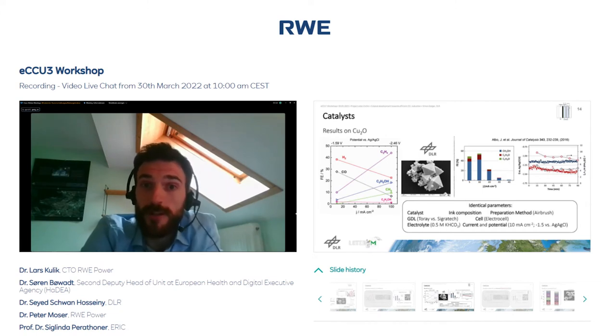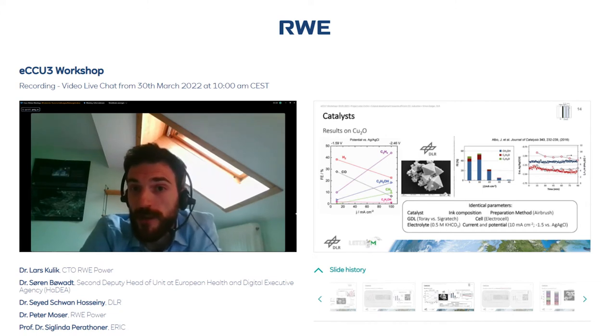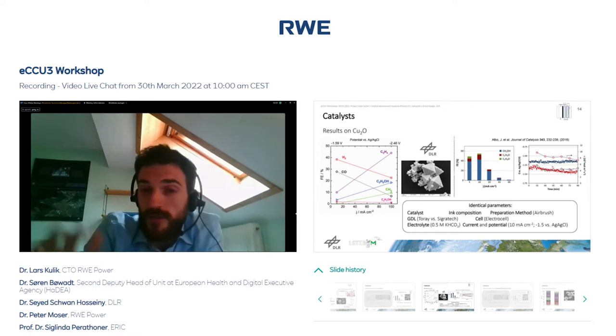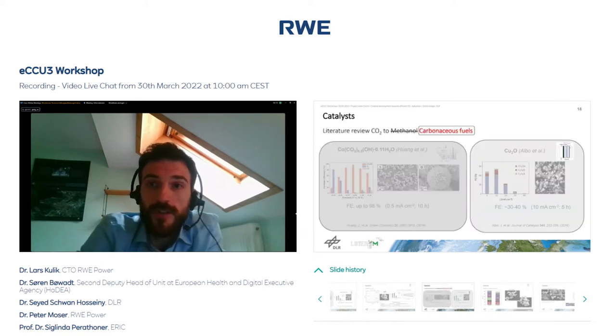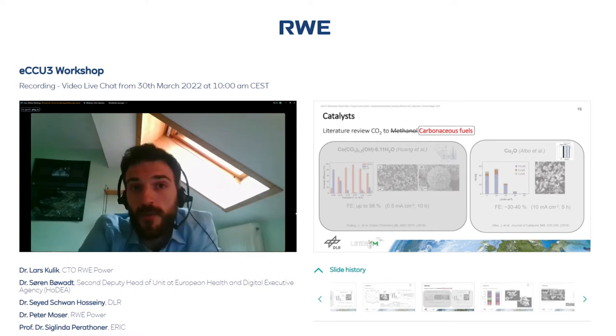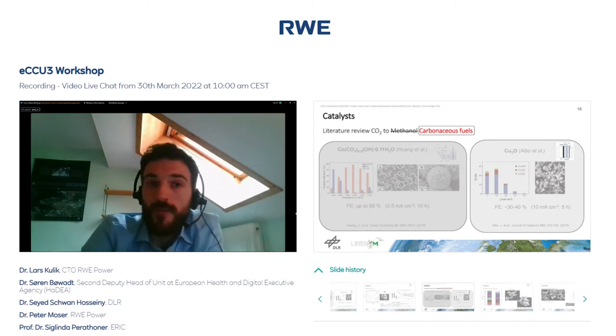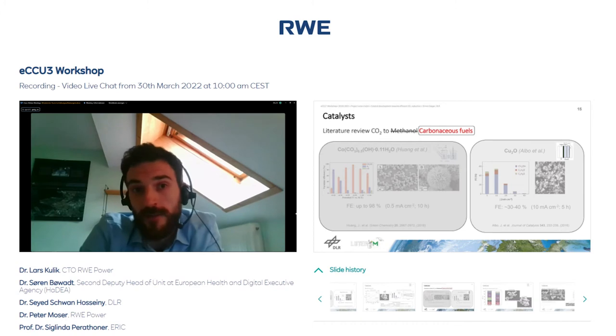good in principle in comparison to this paper, where at 40 milliampere per square centimeter, the amount of carbonaceous fuels was decreasing significantly. And since we want higher current density, this was the initiative to change our goals now. This you can see on slide 15. So we changed the project goal within an amendment to carbonaceous fuel, and from then on would now focus more on ethylene and ethanol, which are as well valuable products, and we could actually produce these.